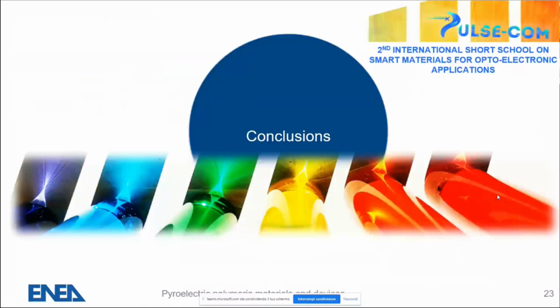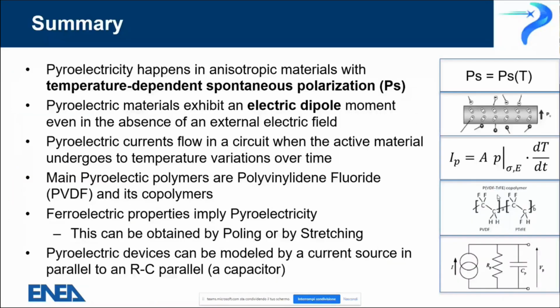This is a small introduction. In conclusion, we can summarize everything. Pyroelectricity depends on spontaneous polarization variations with the temperature. Spontaneous polarization is due to electric dipoles inside the material, so it's a property of the material. Pyroelectric current will vary with the temperature variations proportionally through the pyroelectric coefficient, which itself varies with the temperature. We can have many pyroelectric polymers, but the preferred one is PVDF and its copolymers because of its performance. And pyroelectric devices should be carefully adapted to the external circuit in order to collect their electrical signal.